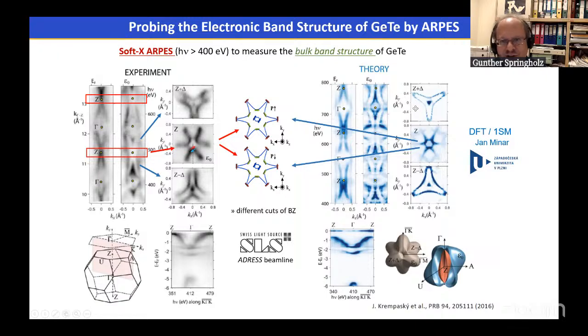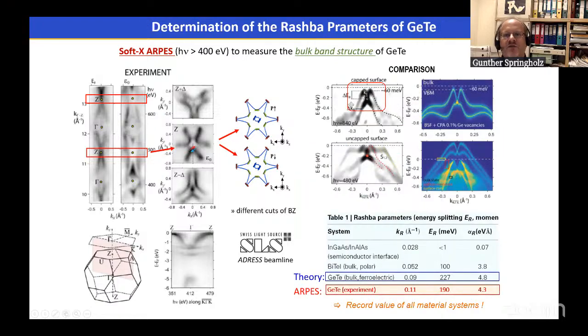And here on the right-hand side are shown the theory DFT calculations performed by Jan Minár's group in Pilsen, and one can see quite good agreement between the experiments and the theoretical calculations. From that, we can verify the Rashba splitting at the Z point of the Brillouin zone, as shown here by the experiments, and measure the Rashba splitting in energy and in momentum. And we have derived from these experiments an experimental value of the Rashba coupling constant of 4.3 eV angstrom, which is quite close to the originally predicted value.